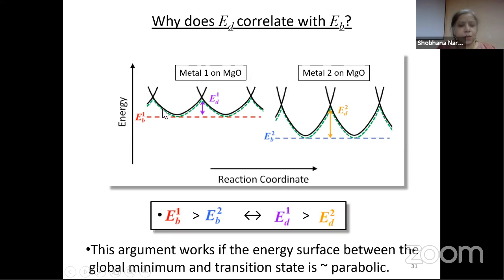About, yeah. Okay, so if you can approximate it by parabolas, then the height, the diffusion barrier, is given by this value, this purple arrow here, and the binding energy is given by the depth at the bottom of the parabola. And from this figure, you can see that if the binding energy becomes more, that is the depth becomes more, the diffusion barrier also becomes more. But this argument works only if the energy surface between the global minimum and the transition state is approximately parabolic.